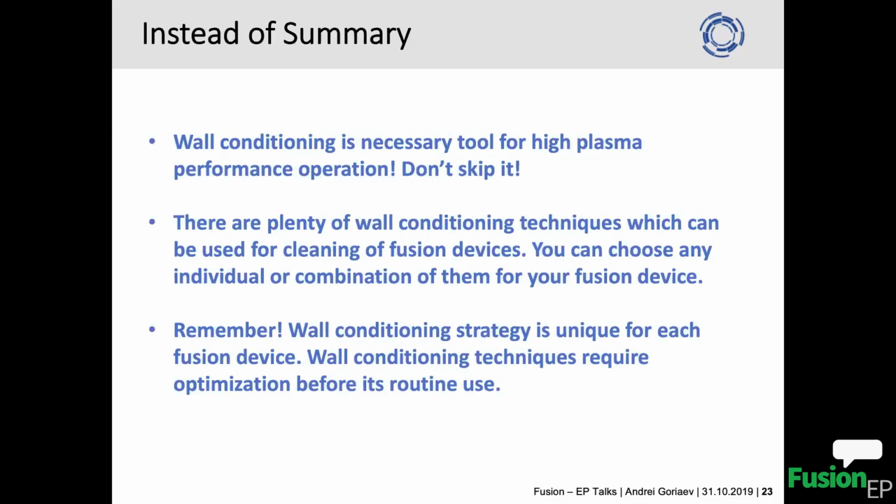For example, we have the same glow discharge anodes installed in THOMAS, and we study the glow discharge breakdown on THOMAS, because glow discharge breakdown in W7-X caused erosion and redeposition of eroded material, and people are complaining that we have some traces of arcing because of glow discharge, so it should be optimized.